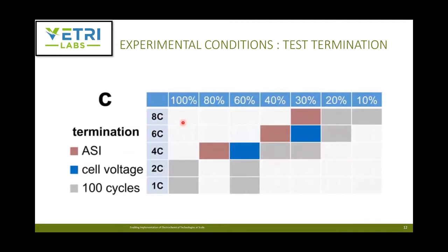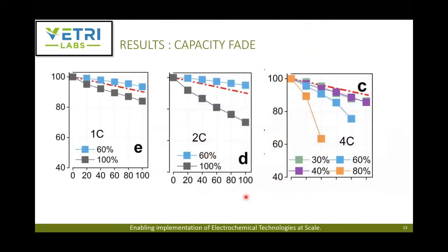Third, test termination versus SOC and charging rate. You can see here, as you go up, you had this impedance rise very fast, and that led to the end of a test. Whereas if you're at low rate, you completed the full 100 cycles. Okay. Now let's go to the results. Here are the results of the different charging rates.